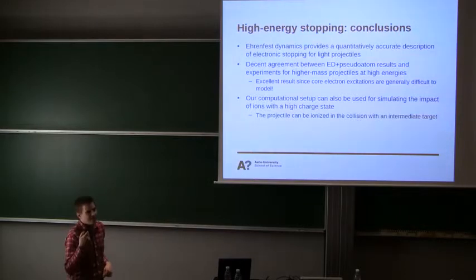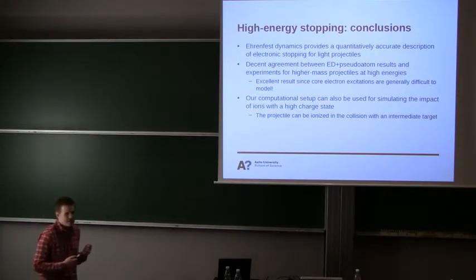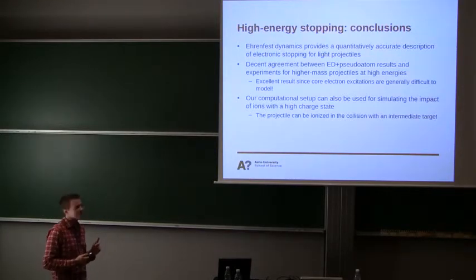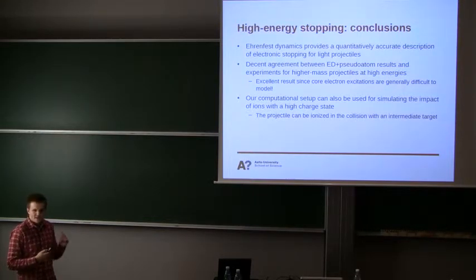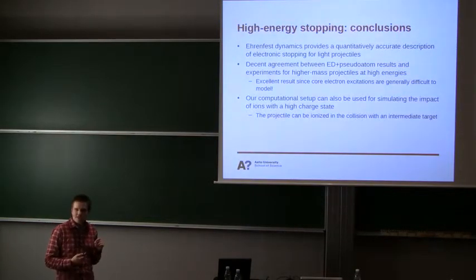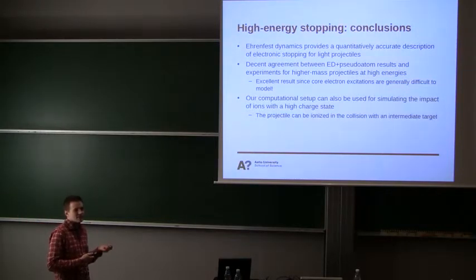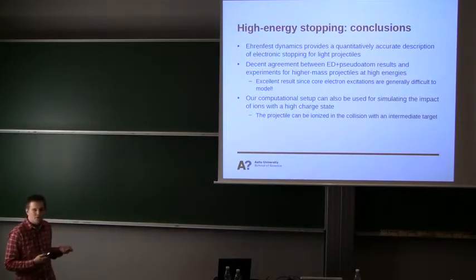So from all of this, we can conclude that Ehrenfest dynamics provides an excellent description of electron stopping, especially for light projectiles. If we include the core states or semi-core states in PAW setups, we find that Ehrenfest dynamics also gives a pretty good description of the stopping for higher mass projectiles at higher energies.